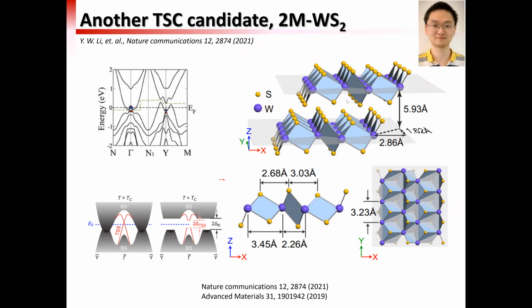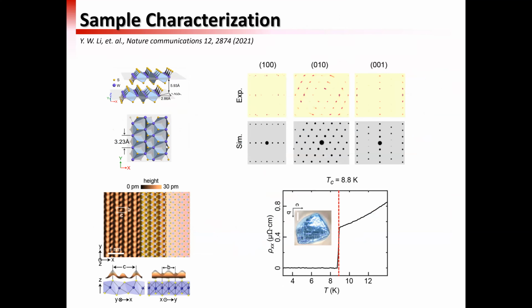But the structure itself is pretty nice. According to our band structure analysis, there is also band inversion happening, so we expect that at the gamma point there should be a topological surface state. Because the transition temperature is pretty high, 8.8 Kelvin, we hope that we can see the superconducting gap opening at the topological surface state, as well as the bulk state. Here is the basic characterization of the sample. Our STM measurements show a very nice surface formed by sulfur chains, without reconstruction.